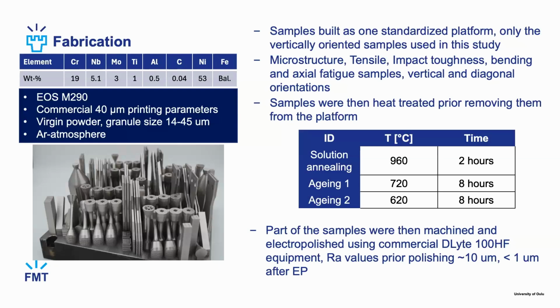We printed samples in vertical and diagonal orientation, and we have bending fatigue, axial fatigue, tensile samples, impact toughness samples, and also some powder samples, but in this study we used only the vertical ones. For the fabrication, we have an SLM printer on our campus, but this one was printed using the EOS M290 system, which is a closed machine, so we cannot really fiddle with it. We just press play, basically, and so the commercial 40-micron printing parameters were used. To make things as clear as possible, we used unused powder with a granular size of 14 to 45 microns, and of course the printing was done in an argon atmosphere.